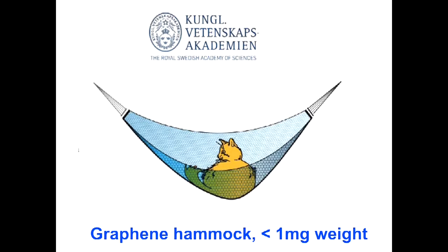which is actually correct if you work it out. If you determine the strength of the monolayer of graphene, you'll see if you have a very light cat and then you imagined getting this with absolutely no defects and strung up as a hammock, it would support that weight. So this shows one of the outstanding properties of these monolayer materials, that because you can prepare them without defects, and the way defect propagation works, you get unusually high strength, basically the fundamental strength of the chemical bonds in